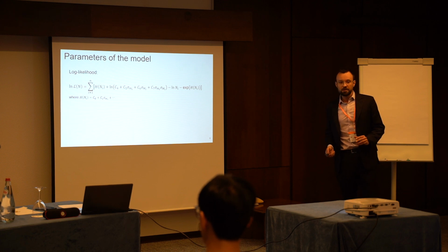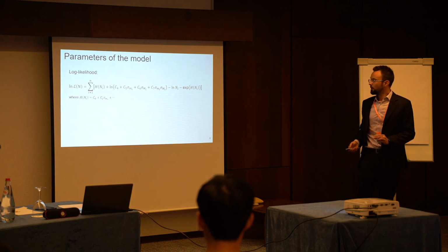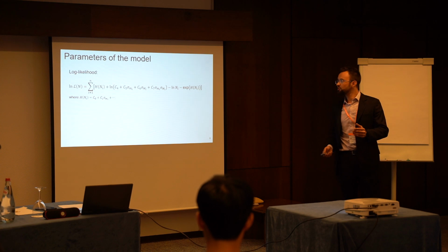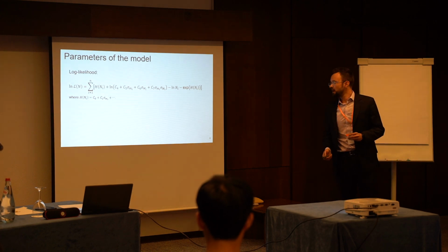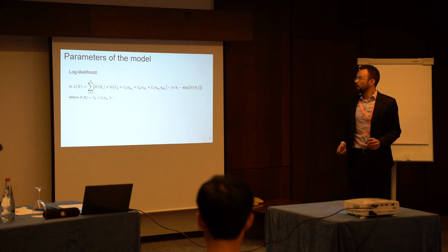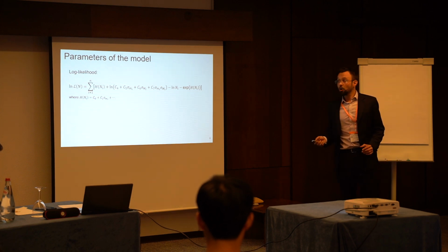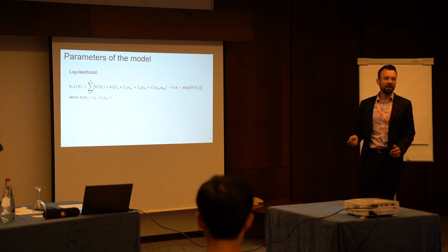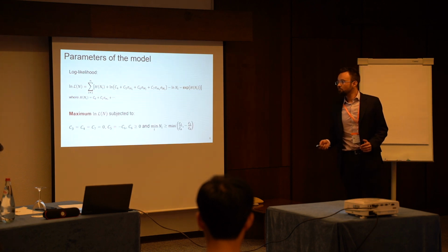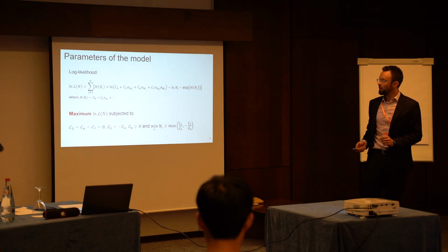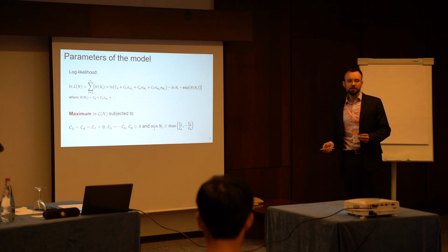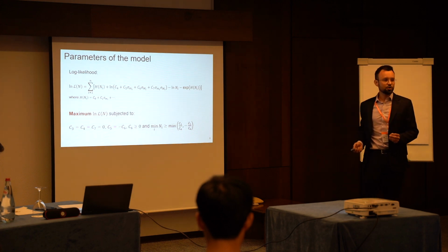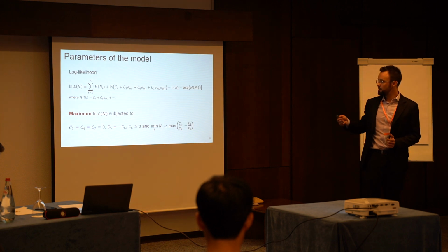These parameters of the model follow a Gumbel distribution and can be determined using maximum log likelihood. Here, the log likelihood is a summation of terms, and its maximum is subject to these constraints. So we can obtain the parameters of the model. Here we need a non-linear optimization to obtain these C parameters.